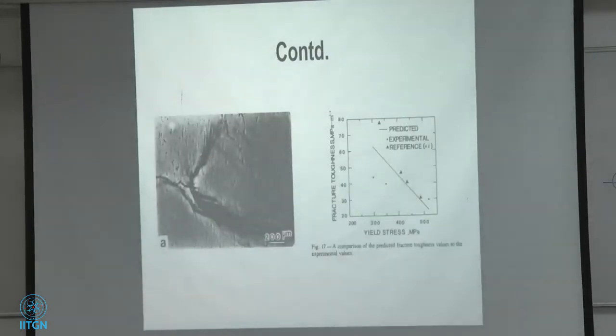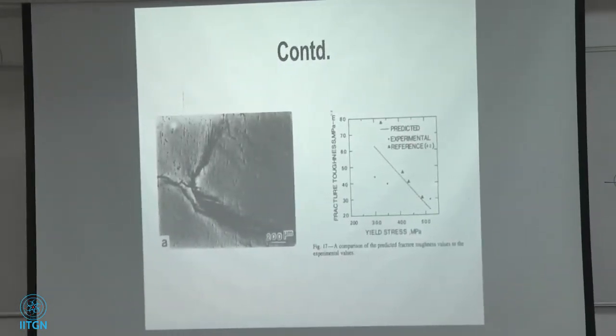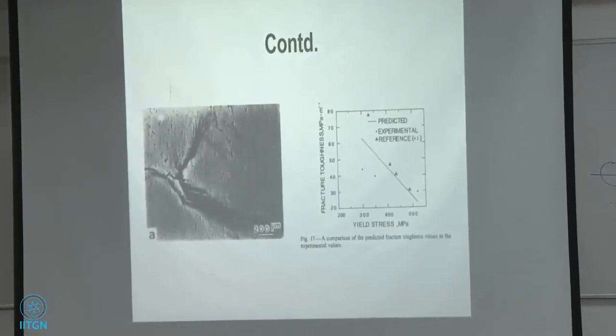And the next one we have picture taken of the plastic zone. So it's not a nice round one like in the books. Well, no, the book also puts this wing-shaped plastic zone. Especially in these kind of materials, you can see you got both this wing and also that wing. So the plastic zone is not necessarily a round, nice plastic zone. The plasticity is spreading along a bunch of planes along this direction, a bunch of planes along this direction. And this is the crack growth direction. Okay? Is it okay, Shinde?